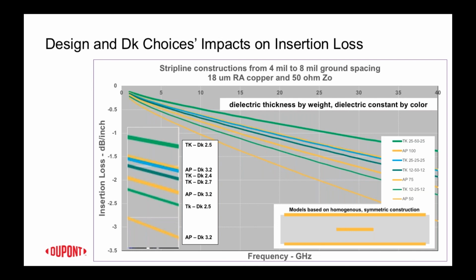The next line down is another different 3 mil potential construction for Pyralux TK with a dielectric constant of 2.7. And it models in between the 2.4 DK value and the Pyralux AP at 75 microns or 3 mils, which is shown next. The last two lines are Pyralux TK and Pyralux AP, each of them at 50 microns thickness for the laminate, or 100 microns ground plane spacing for the construction. 100 microns or 4 mils.